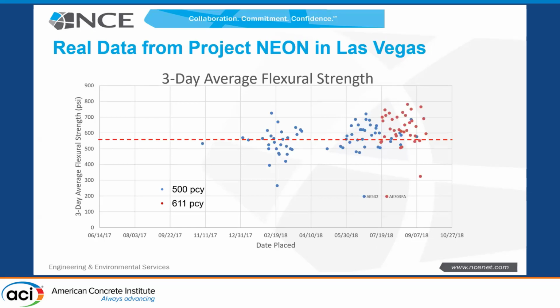This is strength data from 3-day averages. And we switched as we got into summer because this was 100% manufactured sand. That mix started under the heat and a little bit of moisture control issues, I'll say, with the ready mix supplier. They were getting a little stiffening of the mix. So the only other mix they had approved was the 611.